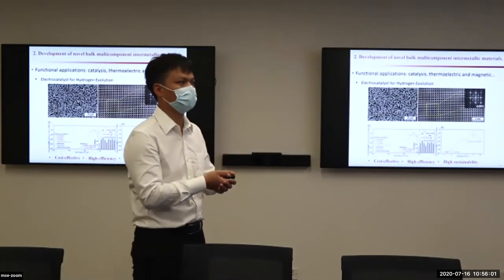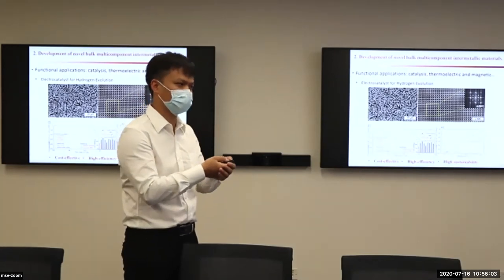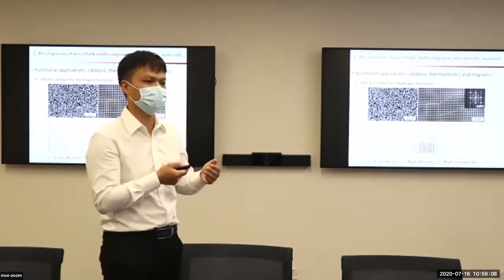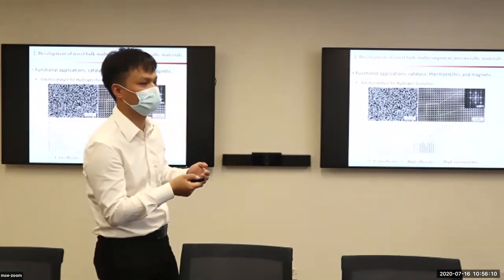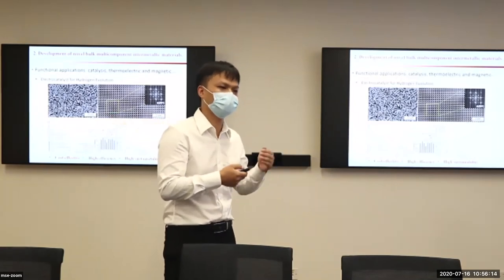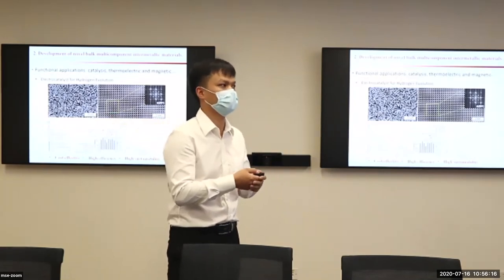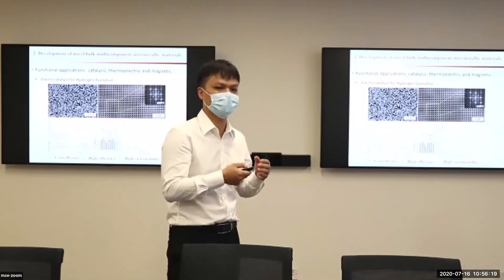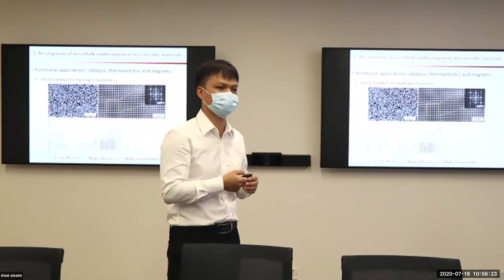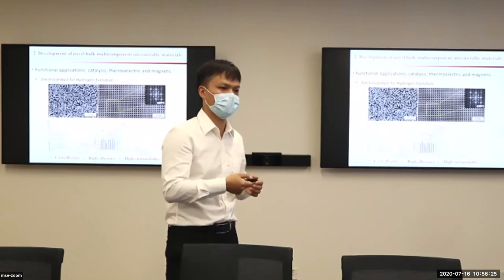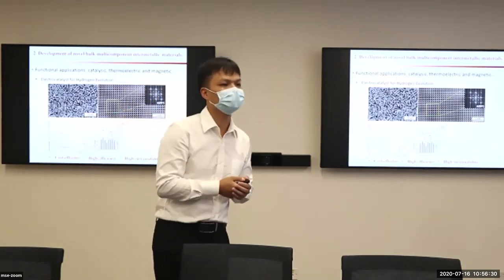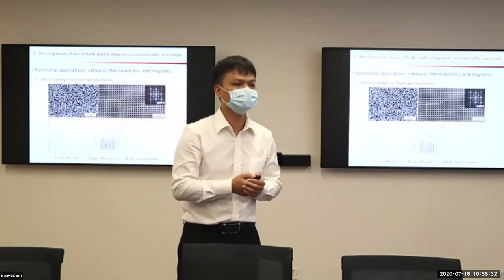Okay. And for this material, we produce it by melt spinning to get the ribbons because we want to refine the dendrite structure. So we need a very rapid cooling rate to refine this dendrite structure, and then we can refine the porous structure, the size of the pores, to increase the reaction activities. So basically you have more like a solid structure with a lot of porosity.